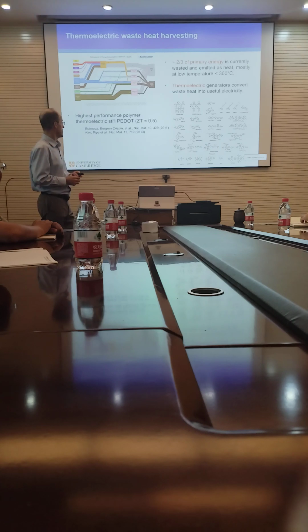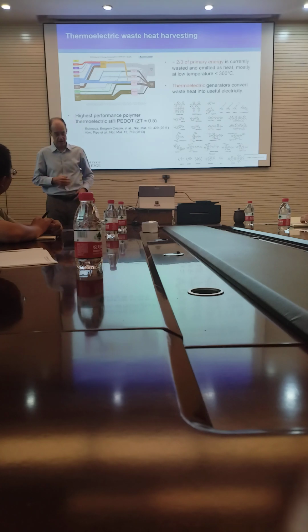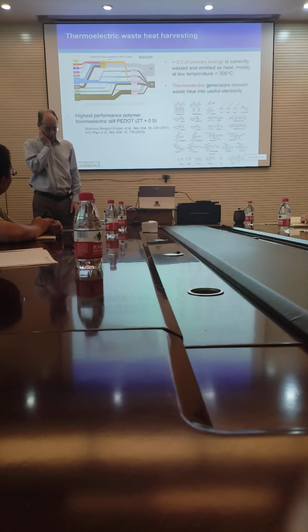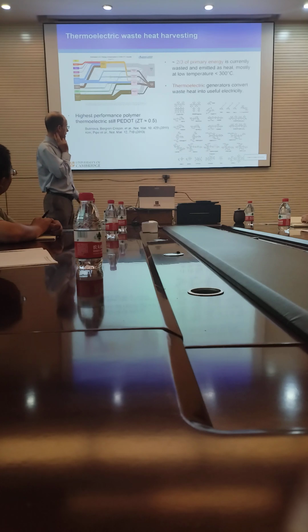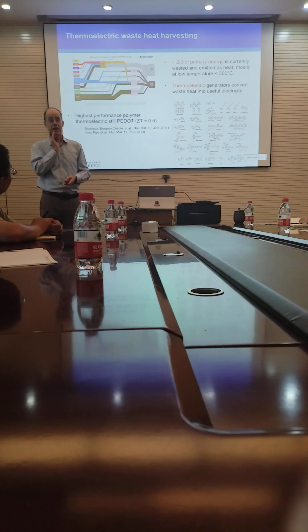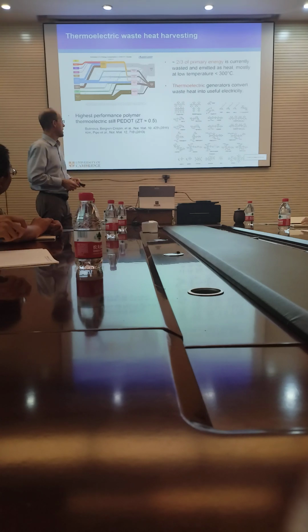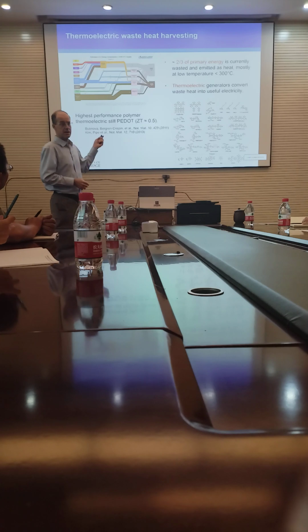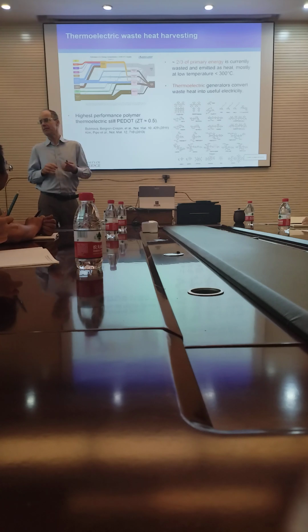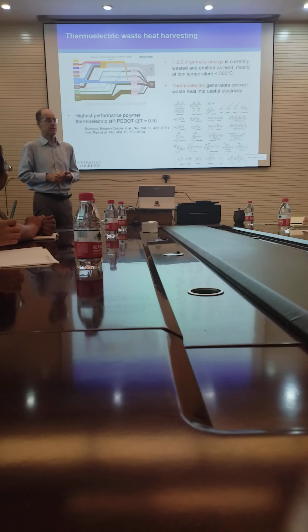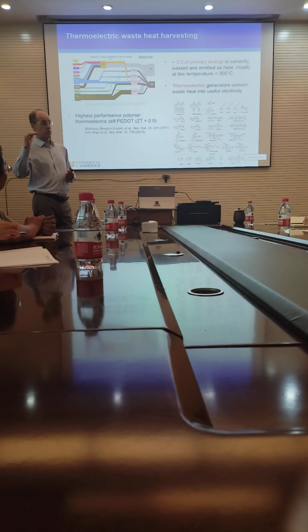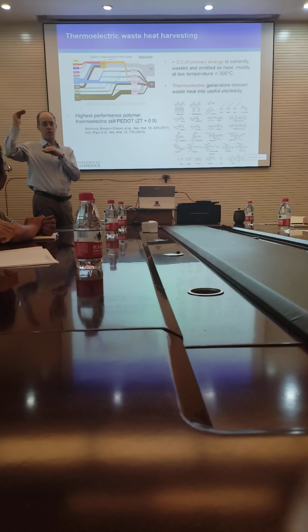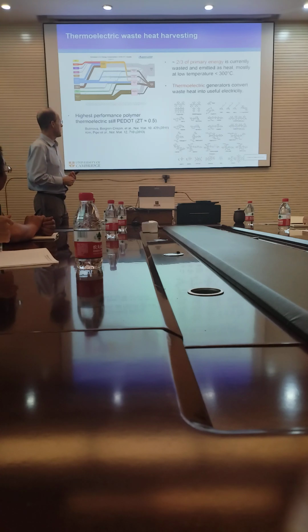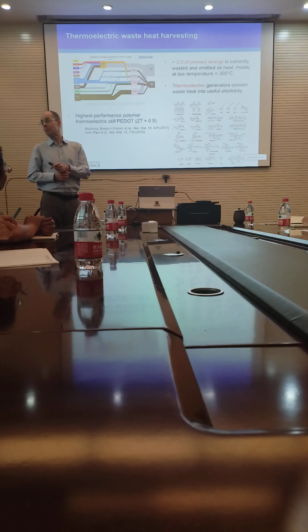I think the interest in organic thermoelectrics probably goes back to these two papers here in 2011. Xavier Crispin and Magnus Berggren's group in Linköping published that PEDOT, a conducting polymer that many of you will know, can be quite a decent thermoelectric material. It has a figure of merit, ZT, I'll explain in a moment what ZT is, of 0.5. The best inorganic thermoelectrics that operate near room temperature have a ZT of about 1. So PEDOT is coming pretty close to the benchmark inorganic thermoelectrics. So there was a lot of excitement at the time about this discovery.